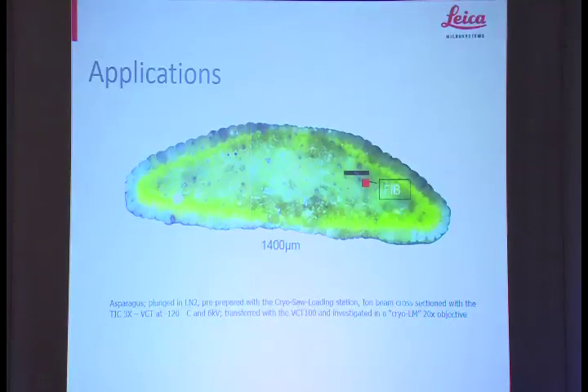To give you an idea, if you focus ion beamed this sample, you would get an area this size. So this led to the thought of maybe broad ion beam milling would be a good step in the processing for FIB techniques. If you want to look at a huge area, why not mill it flat first so you can identify regions of interest and do a correlative type preparation. So you can find the regions of interest before you go to the FIB.